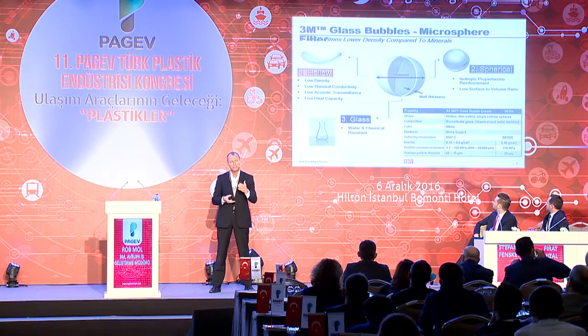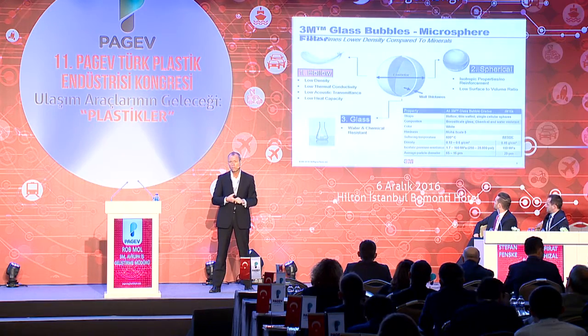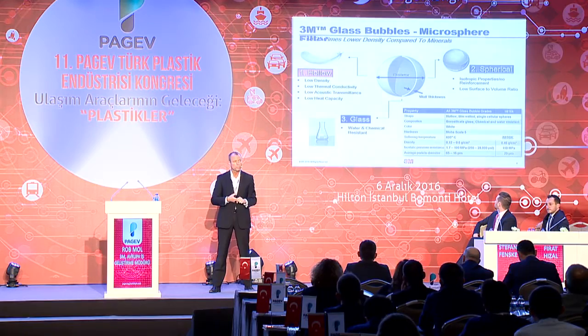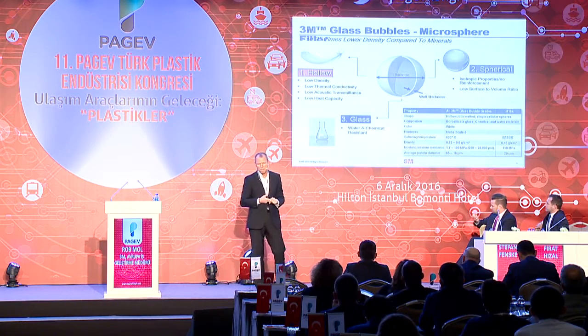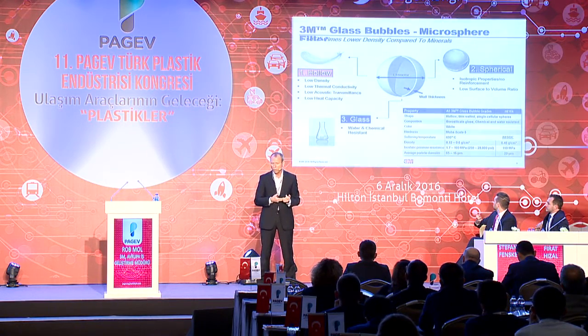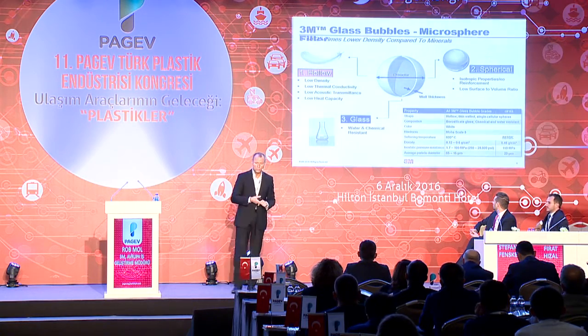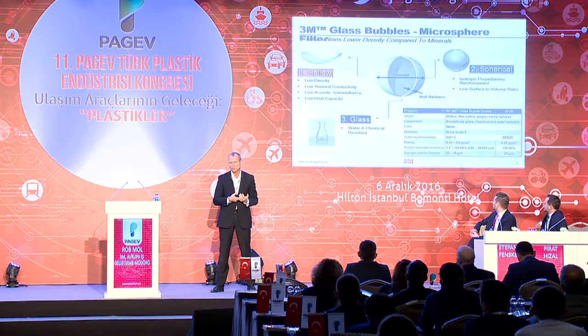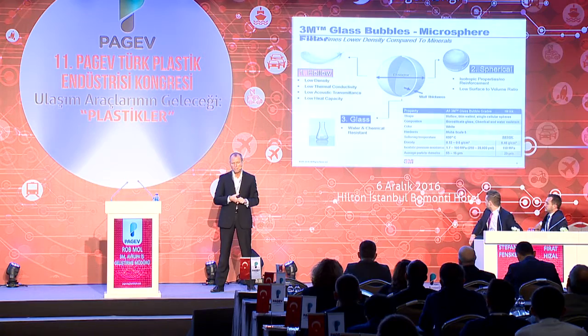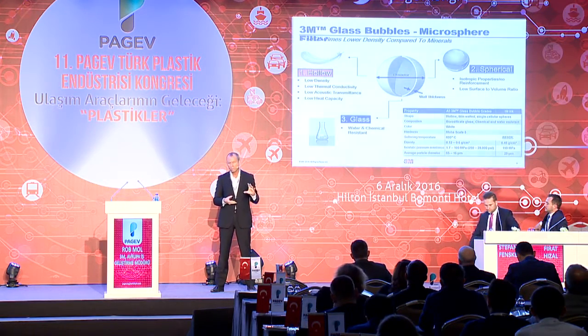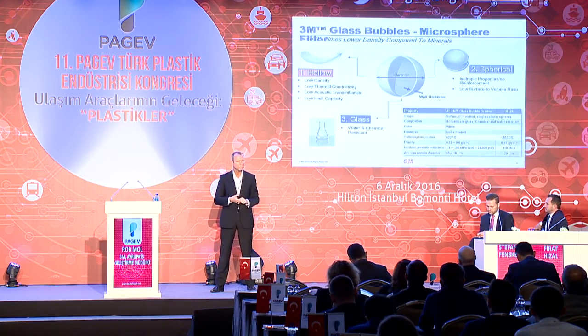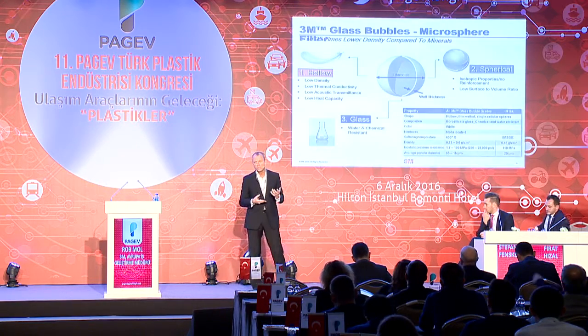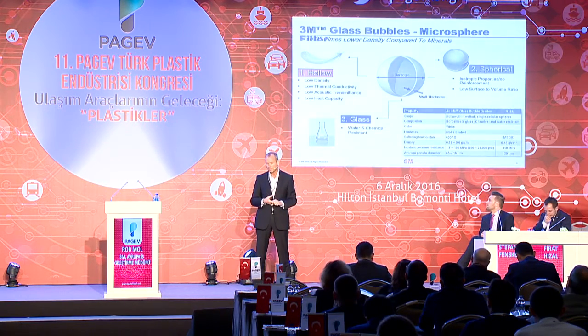Now, the fact that it's hollow means that the density is very low. We have different versions, but the lowest is 0.12 grams per cubic centimeter, which is quite low. That also means that you have low thermal conductivity if you use that filler in a plastic material, and also low acoustic transmittance. The fact that it is spherical, that it is round, means that the dimensional stability is improved versus normal fillers, and there is less warpage and less shrinkage in the material if you apply that.